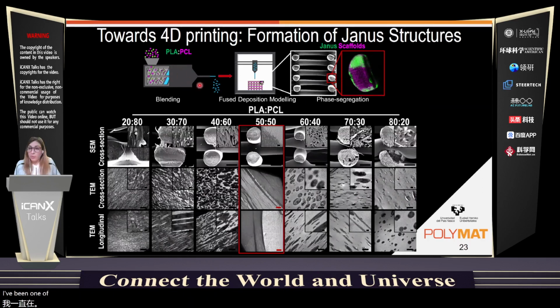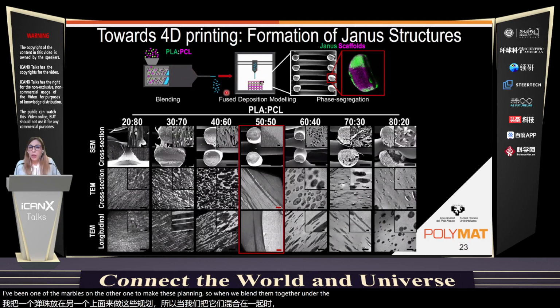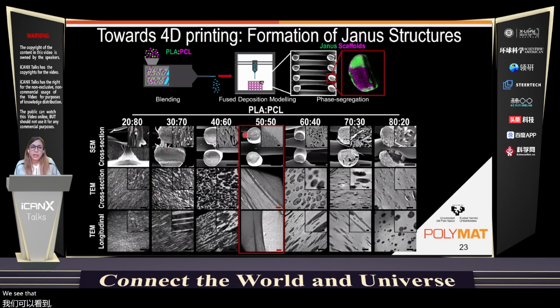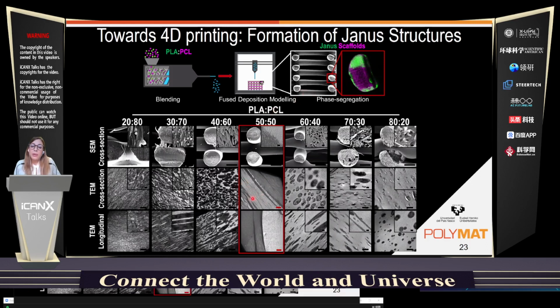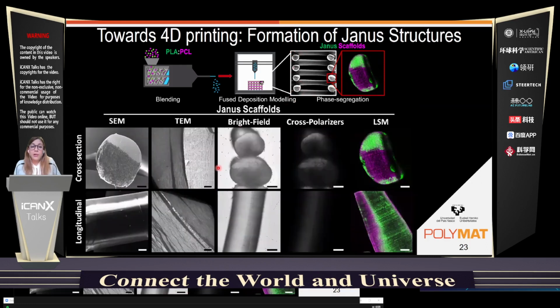being one of them amorphous and the other one semi-crystalline. So when we blend them together and we 3D print them, we see that depending on the polymer ratio that we use, this one will phase segregate following a nucleation and growth pattern. However, at a 50-50 composition, we were able to see the formation of these Janus scaffolds, having one phase rich in PLA and the other one rich in PCL. Now, this was homogeneous along the whole entire scaffold and under the same direction.